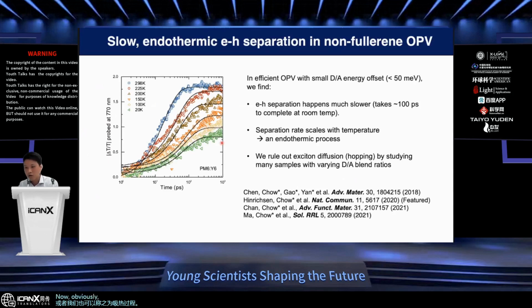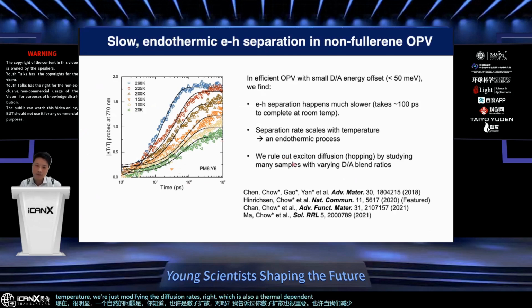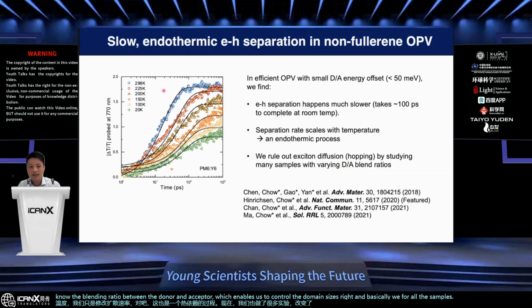Now, obviously, a natural question is whether maybe it's the exciton diffusion. I told you that exciton diffusion is also important. Maybe when we decrease the temperature, we're just modifying the diffusion rate, which is also a temperature-dependent process. Now, we also did a lot of experiments where we changed the blending ratio between the donor and acceptor, which enables us to control the domain sizes. For all the samples, even with very, very small domain sizes, we also see this temperature dependence. That gives us an indication that it is the interfacial charge separation that is indeed both slow and also temperature dependent.